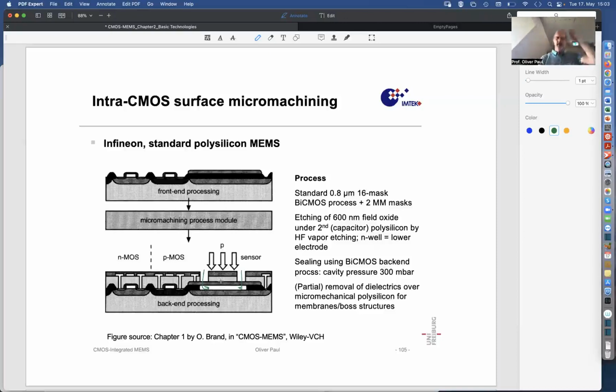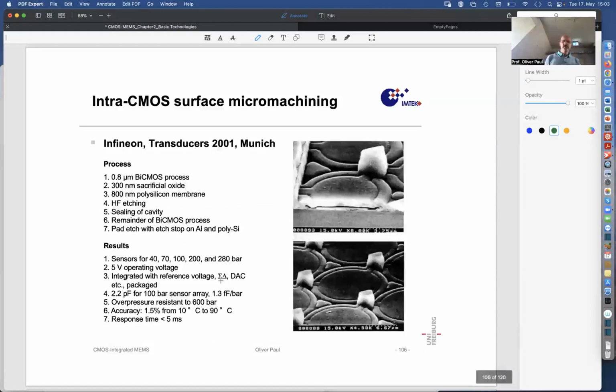So this is a pressure sensor, and we can look at some structures here. Again, sacrificial etching and SEM pictures, scanning electron microscopy micrographs with this removed oxide, and then here a slightly thicker polysilicon. You see also here the area where actually the oxide was etched away from below. There were certainly on the front also such openings that allow to reach that oxide. And then during the growth of the other dielectric layers up to the passivation, those holes were sealed again, and the cavity etched previously is therefore sealed. And these membranes are pressure sensors.